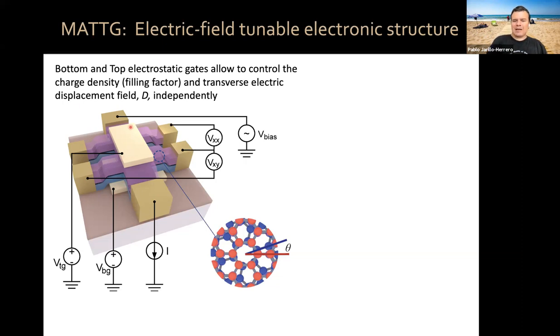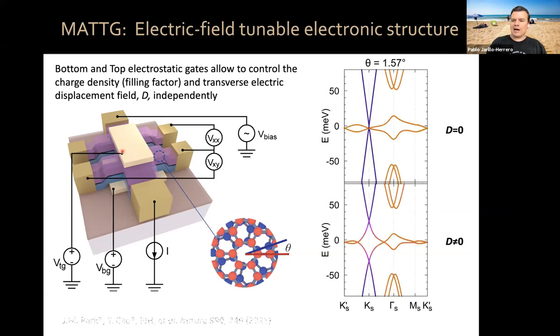When you apply a finite electric displacement field, then you break the mirror symmetry, and as a result, you hybridize your flat band and your massless Dirac bands. So with a finite electric displacement field, you have a hybridization of this band structure. That's going to give you additional tunability, because we can tune the electronic structure, so we're going to be able to tune the properties of the system.